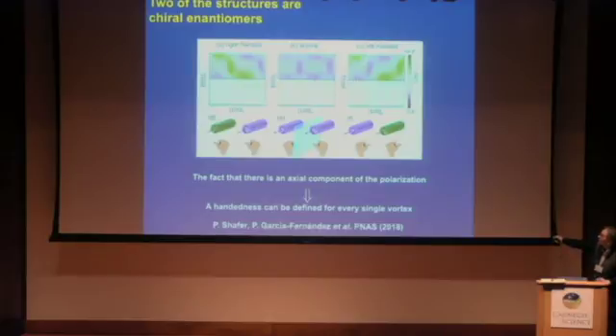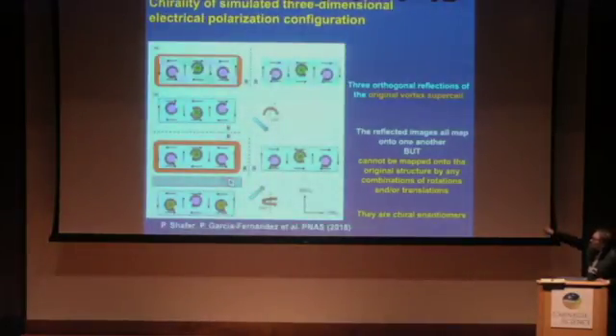So we can take, for instance, one of them here, and this is the original one, the one that is here surrounded by this orange square here, and we can see how, and we are taking three mirror reflections. One is this, another one is this, and another one is this. So we can see how the reflected images all map onto each other, but we cannot map any of the reflected images into the original one just by doing rotations or translations. So the structures with this axial component of the polarization are chiral.